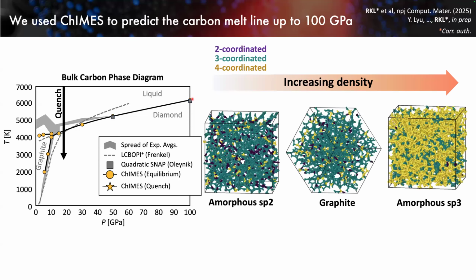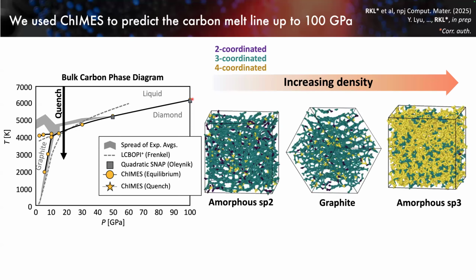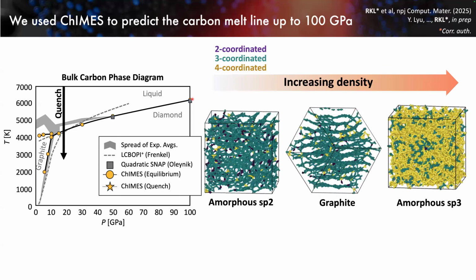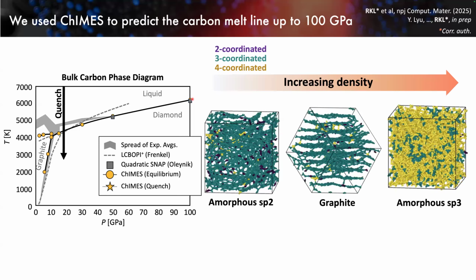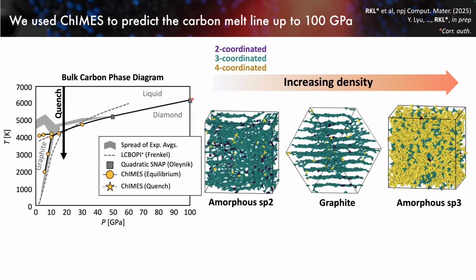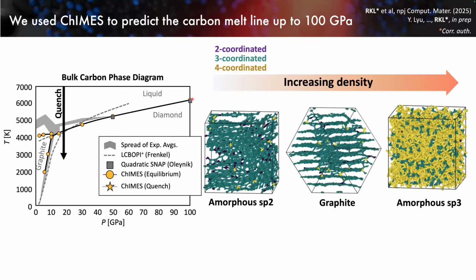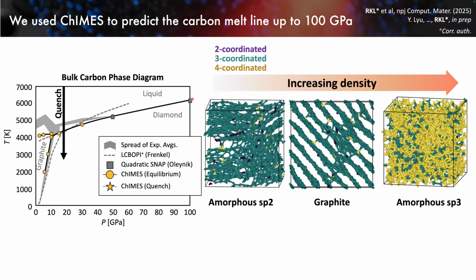We run those simulations, and as time goes on, they start to solidify. Based off of the solid phase we get and the PV curves associated with the suite of densities we run these calculations at, we can draw a kinetically limiting graphite diamond phase boundary. So that's basically what this is here.